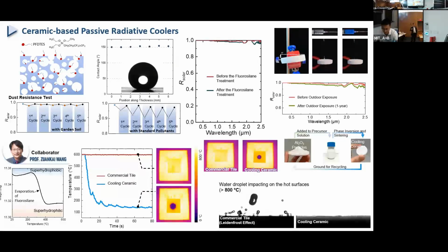But after my collaborator added the material coating on the cooling ceramic, we found that when we drop water onto our cooling ceramic, it is totally super hydrophilic and the water is totally absorbed by the surface. In this way, we can use the evaporative cooling effect to reduce the surface temperature of the cooling ceramic compared to the commercial tile. So this is another highlight. These three slides show another functionality of the cooling ceramic: the material can be recycled and reused to make another cooling ceramic.